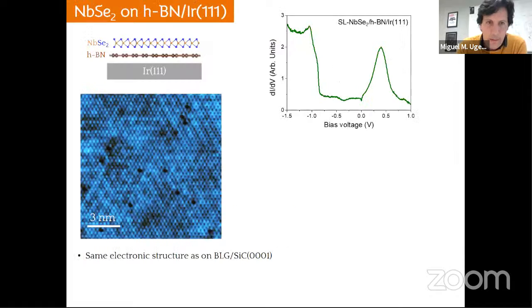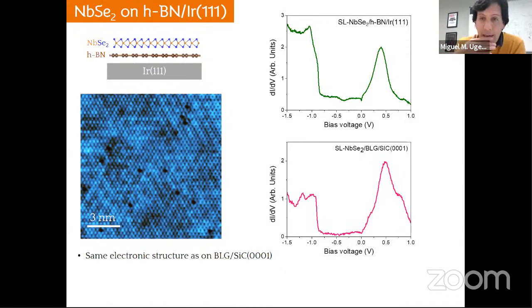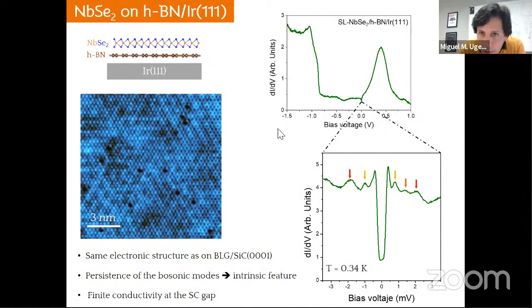In order to rule out spurious effects from the substrate, because we have done all the experiments on bilayer graphene, we have studied this having a single layer of hBN between the substrate and niobium diselenide. The electronic structure on the larger scale is quite similar. It's actually identical. The charge density wave is preserved in the system. If you look around the Fermi level, you see that the superconductivity is preserved as well. And we also see these bosonic mode features.